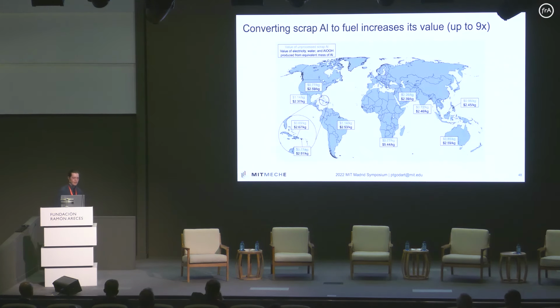So we did a simple case study and looked at a couple different countries and compared the scrap price to some conservative estimates for the profit that could be made by selling the aluminum oxyhydroxide, the heat, and the hydrogen, possibly converting those as well to potable water and selling those at utility rates. And what we see is that in all cases, no matter where we look, we can generate several times the value of the input scrap aluminum itself. And that's the average scrap aluminum price.